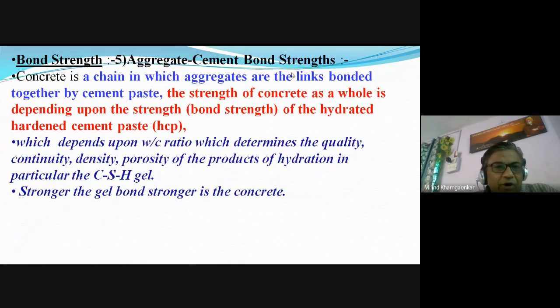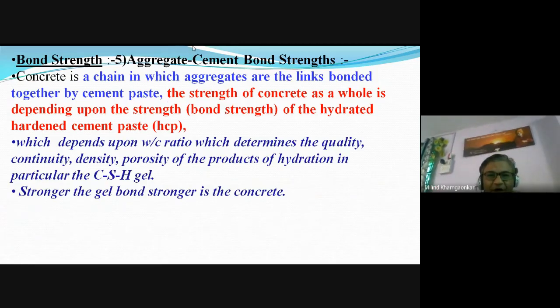The aggregate cement bond strength is also important. Concrete is a chain in which aggregates are links bonded together by the cement paste. The strength of the concrete as a whole depends upon the bond strength of the hydrated hardened paste. Therefore, it depends on the water cement ratio. So friends, you all know the importance of the water cement ratio. Lower the water cement ratio, more will be the bond strength. Therefore, the bond between the cement paste and the aggregate, or between aggregate to aggregate, also depends on the water cement ratio.